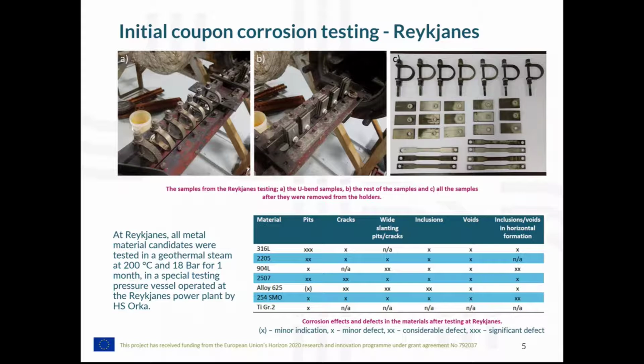And on the images on the top, you can see the samples, the two pictures on the left as they are leaving the pressure vessel, and on the right you see them all laid out. And all the materials were somewhat affected by the testing, which is of course to be expected. And I've laid down the defects that we observed after testing, and what we were mostly seeing were various pits,